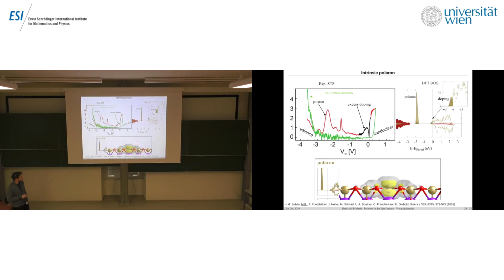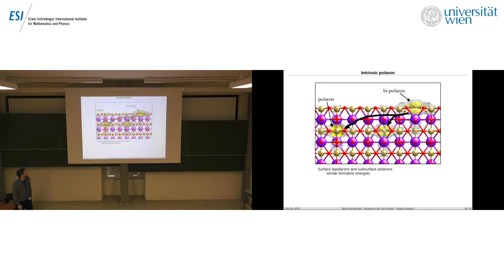So to see this polaronic peak in the calculations, you have to be careful and start to put some distortions there, otherwise you get the worse solution, which is with the delocalized electron. And in the experiment, you have to investigate down to low energies with respect to the Fermi energy. Otherwise, you only focus on the two-dimensional electron gas. I didn't tell you everything about this.